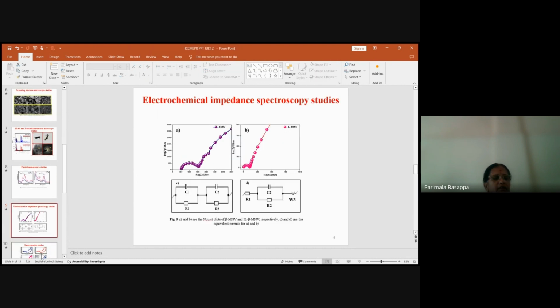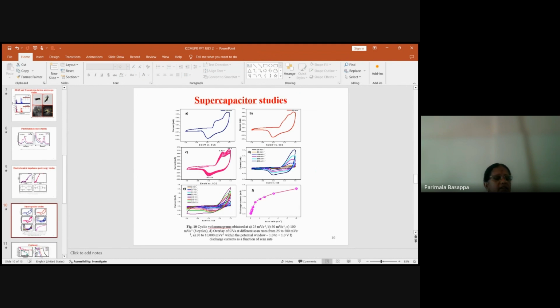Coming to the electrochemical impedance studies we have carried out, CVs are used for this. This is beta MNV, and ionic liquid beta MNV. You can see a duck-shaped CV here. This shows that the conductance is more in the case of ionic liquid beta manganese vanadate. So CV studies were used to study the supercapacitor behavior. This is the anodic oxidation peak, and this is the cathodic reduction peak. You can see 6 different cycles were carried out here.